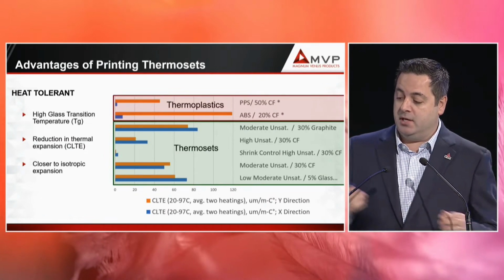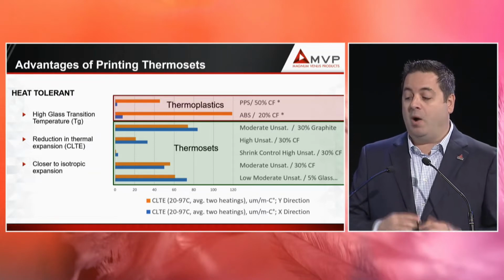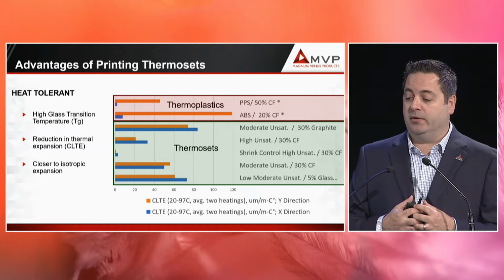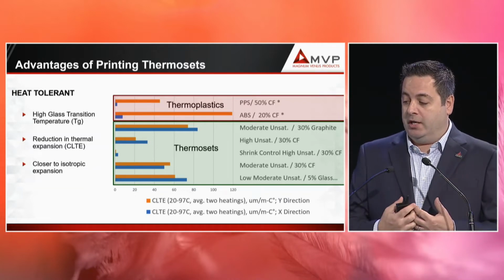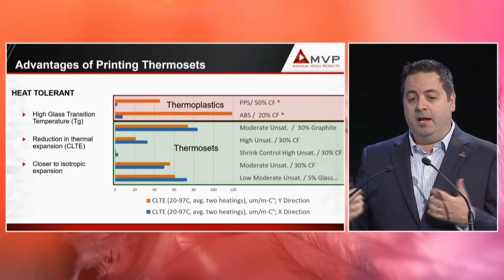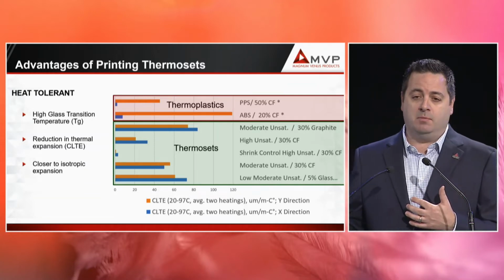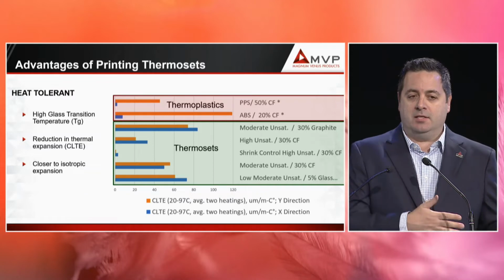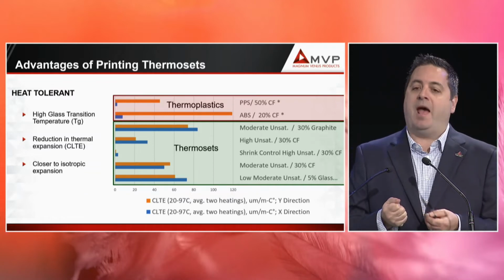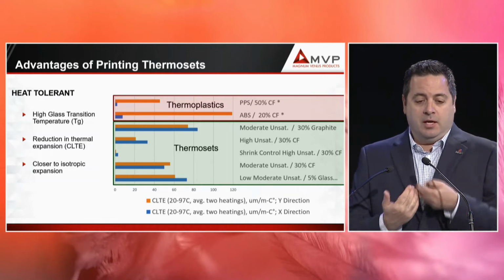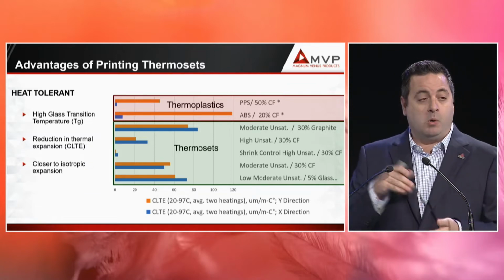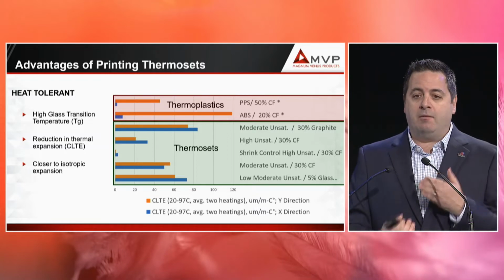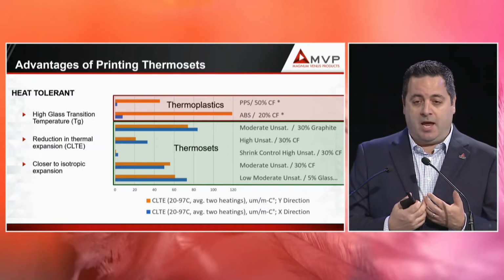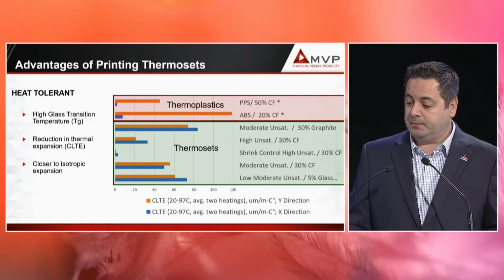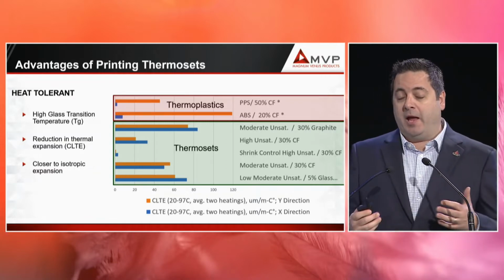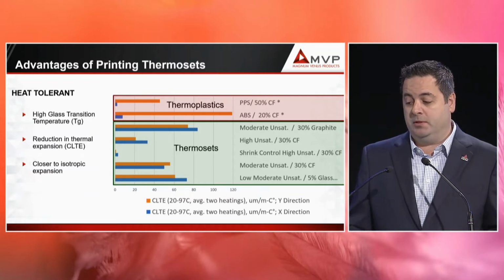And so this graph illustrates in the orange is the Y direction expansion versus the X direction. In the top two examples, you have this really short expansion in the X direction and a longer expansion in the Y direction. In many cases, 10 times more. And that's really because as you're printing, the fibers that are contained inside of the material are lining up in that X direction, and they're holding back that print. And they don't do that in the Y direction, and so you get this enormous distribution of change in your print or in your mold, whatever it is. In thermosets, that retention is much higher because of the entanglement and because you're using a chemical reaction. So we're getting closer to isotropic expansion, and we do have a few other experimental materials we're working with that hope to get to isotropic expansion.